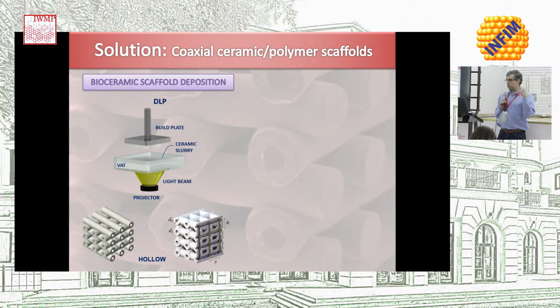Well, we will be using the high resolution of DLP to produce structures of ceramic material which are hollow. The struts of this material will be hollow, so we will have two sets of porosities, the one on the outside of the struts and the one on the inside, the channels. And we were producing two types of structures, one which is similar to the Robocast structure, in this log pile structure, but with channels inside. And then the one that I'm showing on the right, in which the channels are interconnected in the three directions of space, because the struts form an interpenetrated network.